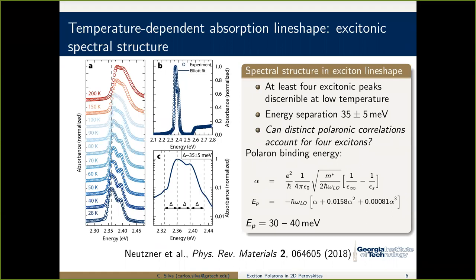And if that's the polaron binding energy, we can predict it also simply from this sort of Fröhlich type of model, with this Fröhlich coefficient that I introduced at the beginning, and a perturbative treatment. You see the numbers here. You predict this polaron binding energy that matches the spacing between these exciton peaks. So at this point, it's nothing more than a hypothesis. Can it be that we're seeing different excitons with a binding energy that differs by multiples of a polaron binding energy? That was the hypothesis in this Physical Review Materials paper in 2018.